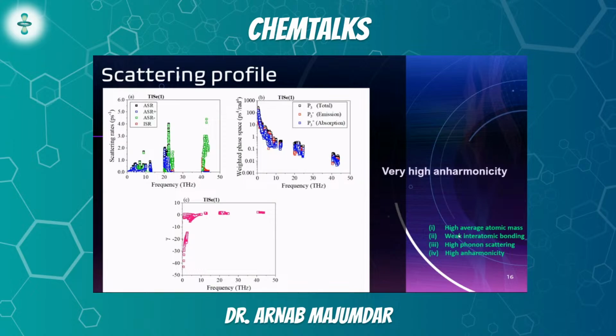That means now all my 4 criteria have been satisfied. So I have high average atomic mass, weak interatomic bonding, high phonon scattering, and high anharmonicity. So just by looking at these graphs, I can predict that maybe the lattice thermal conductivity, kappa L, will be quite low, because that's what our goal is.